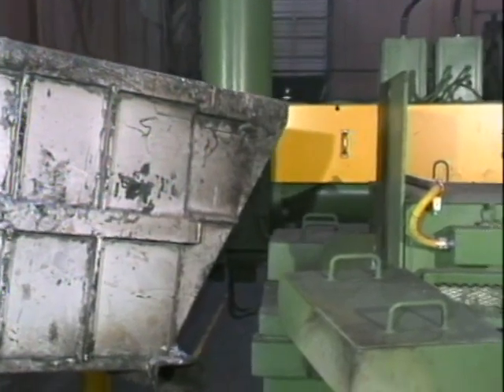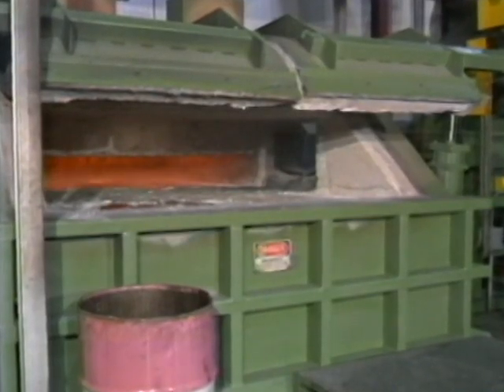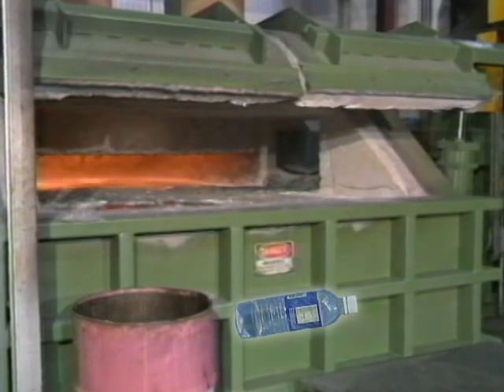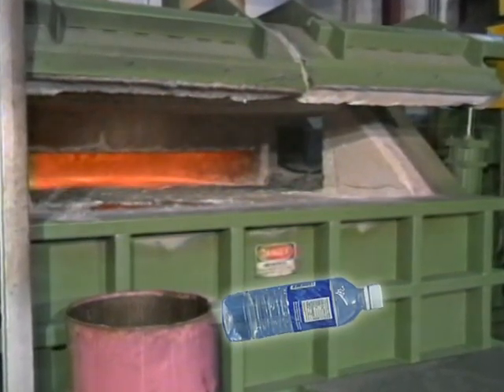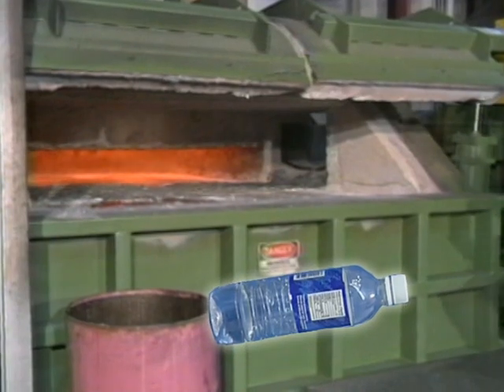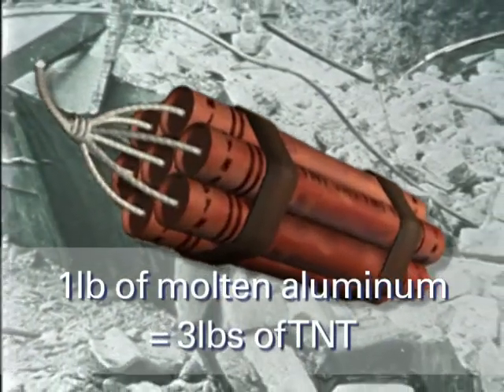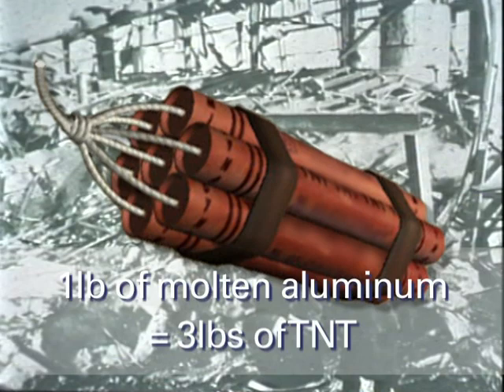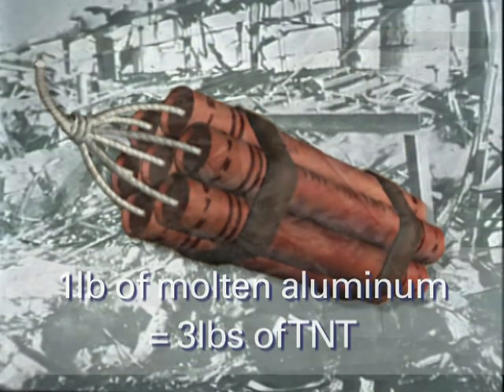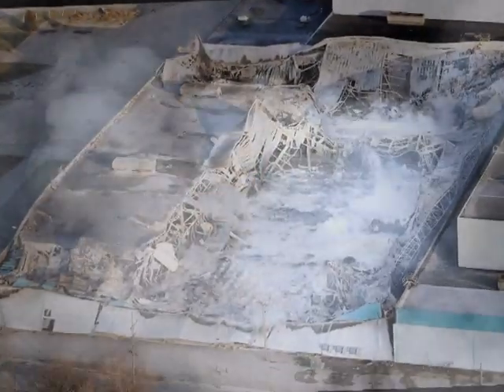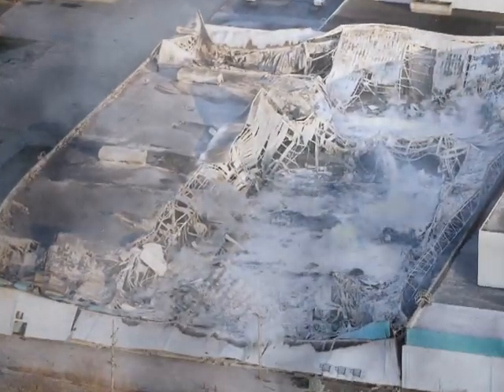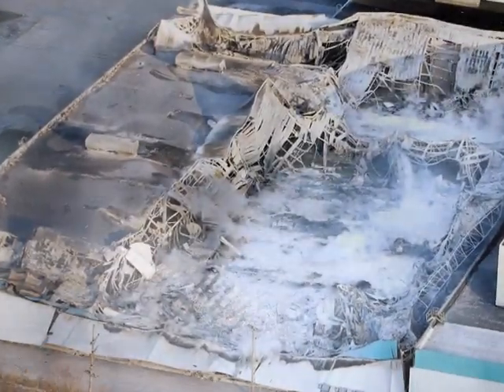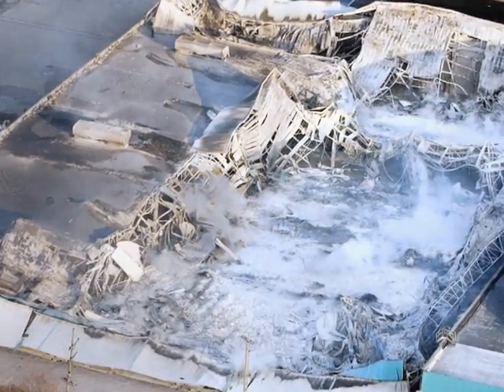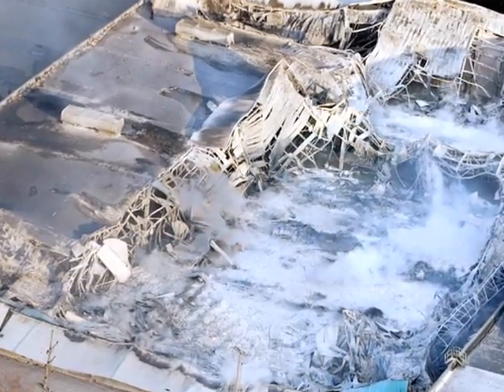The container of water, submerged beneath nearly 50,000 pounds of molten aluminum, expanded 2,500 times. Changing to steam, the water vaporized the molten aluminum, resulting in a massive explosion. 1 pound of molten aluminum has the explosive capacity of 3 pounds of TNT if water becomes trapped beneath it. That's a worst-case scenario. This furnace explosion resulted in the death of 2 workers. 14 others were seriously injured. The explosion was heard 55 miles away. Here's what was left of the plant the next day.